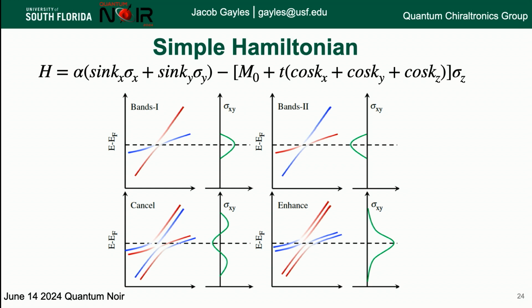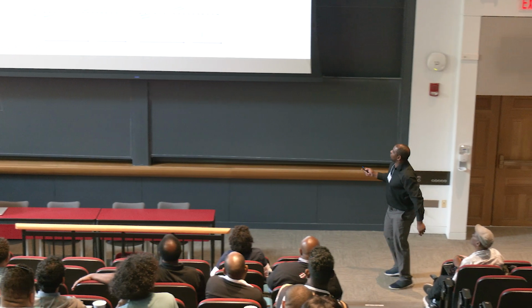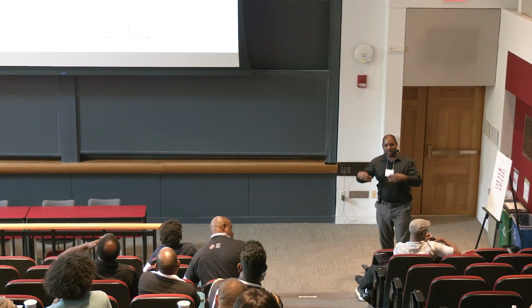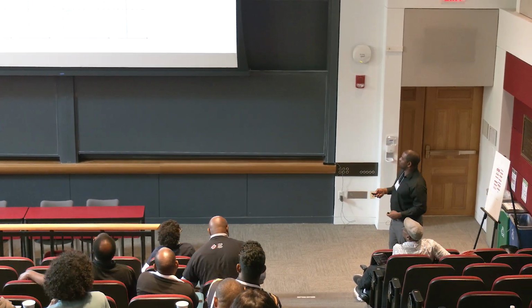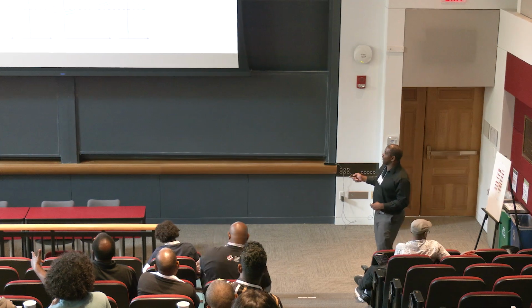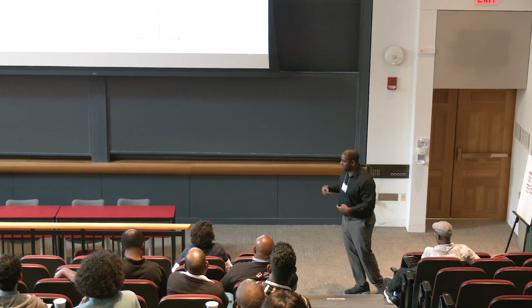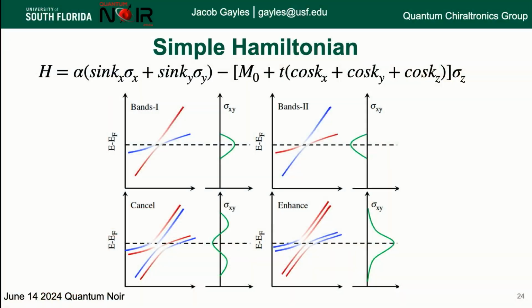Now, of course, one of the big things which was the trouble in my postdoc was how to increase the size of this anomalous Hall effect, right? And what happened was we were mostly here for most of the time. So you can add more bands in, and if you change the chirality on one band that's opposite of the other, then essentially you get a canceling effect. So if you want to systematically increase the size of this anomalous Hall effect, if you're interested in terms of the devices, then you can enhance it by using the same chirality. This is completely inherent to the symmetry of your crystal.